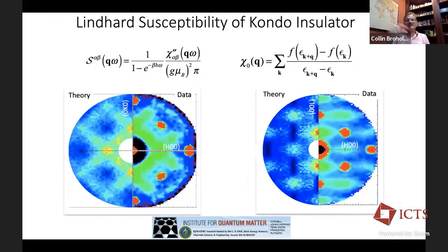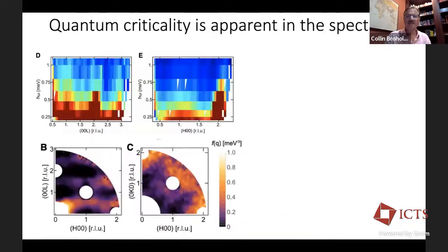And we can understand the wave vector dependence of the magnetic inelastic scattering in terms of simply a Lindhard susceptibility with a phenomenological band structure. We can reproduce many of the features that are seen experimentally. And so it seems that incomplete nesting conditions can give rise to these kinds of momentum dependencies. But yes, no indication of a long-range ordering.